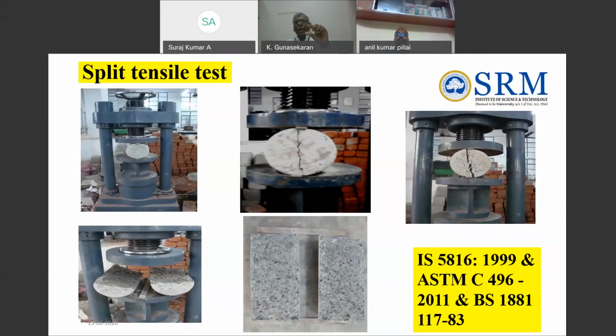So in order to reduce the magnitude of high compressive stresses near the point of application of the load, narrow packing strips of suitable material, normally plywood, having 25 mm width and 3 mm thickness, should be placed between the specimen and the loading platen of the testing machine. So this is the reason why we are placing the packing strips. The packing strips should be soft enough to allow distribution of load over a reasonable area. That is normally plywood of 25 mm width and 3 mm thickness along the length of your cylinder.